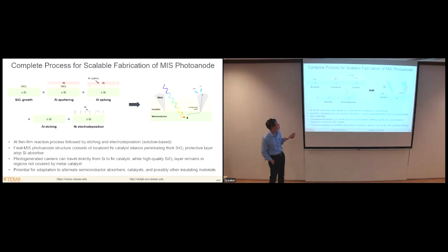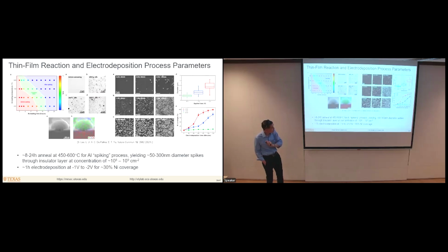The full process to make photoelectrodes, in this case photoanodes, is that you have silicon, you oxidize it, deposit aluminum, anneal it to form these spikes, etch the aluminum away, and then fill those voids using electrodeposition, which is certainly a cheap and scalable technique. We did this with nickel, which is a good enough catalyst for the oxygen evolution reaction. So you get structures like this, where the light can penetrate through the exposed areas. You create electron hole pairs, and then the holes can move easily through to the catalyst to participate in the oxygen evolution reaction.